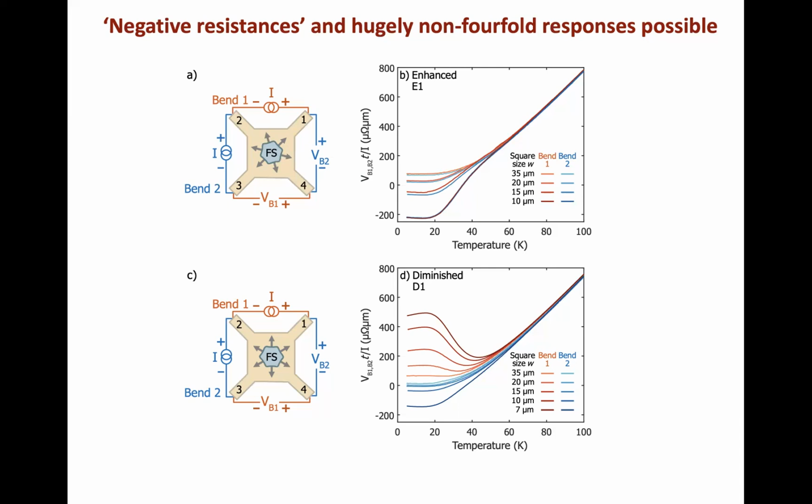So that really sets a limit. The momentum-relaxing mean free path is already down to a few microns, or a couple of microns, say at 70 Kelvin. I need to look again. Therefore, you would need a momentum-conserving mean free path much less than that. And it's just going to be, again, a balance. That would need, again, to be a detailed electron-phonon calculation, I think. But in principle, you might be able to find something, right?